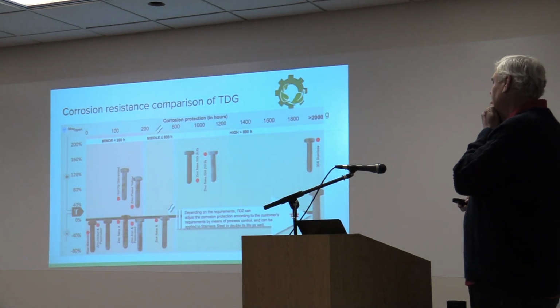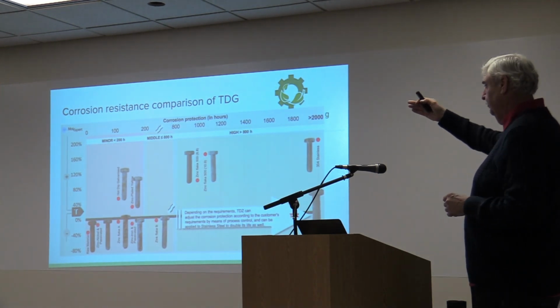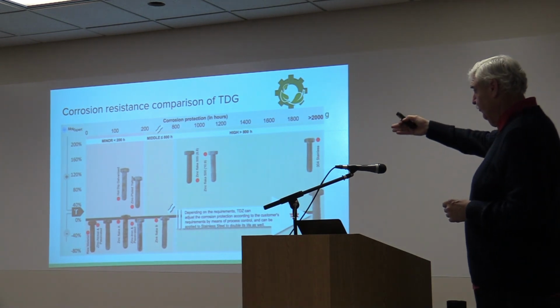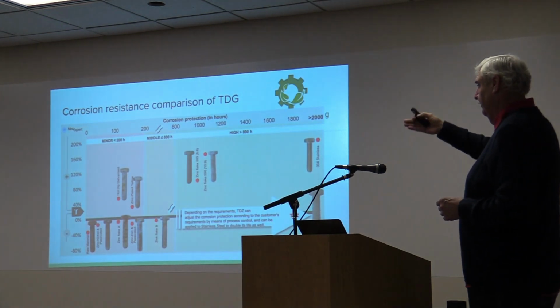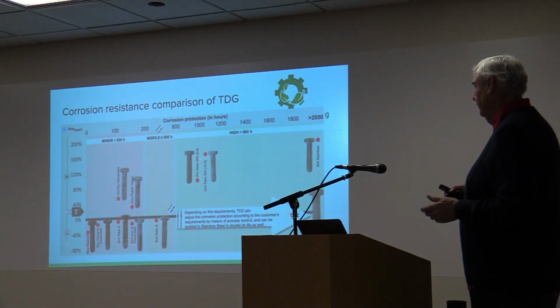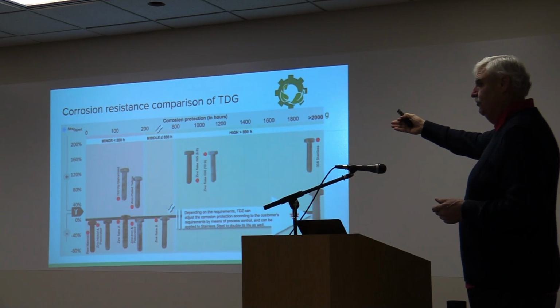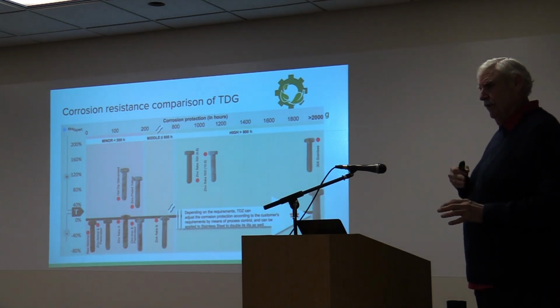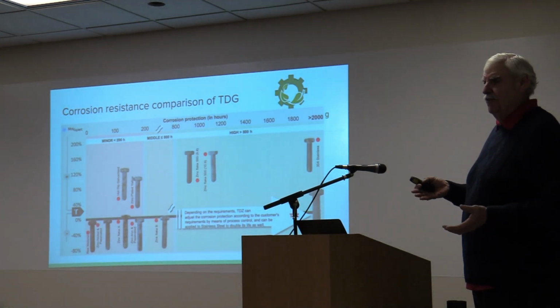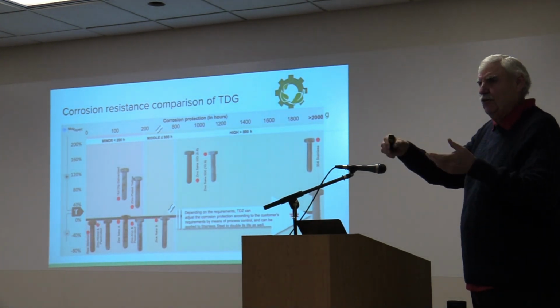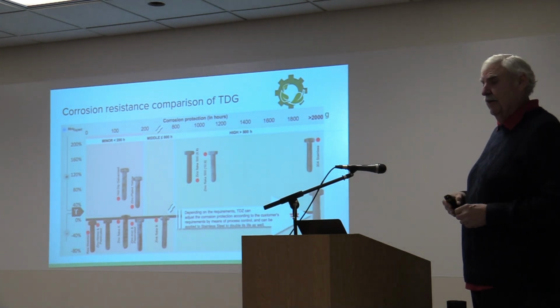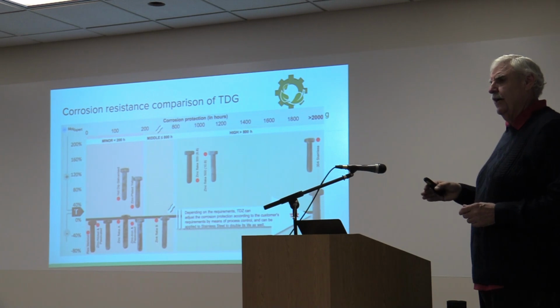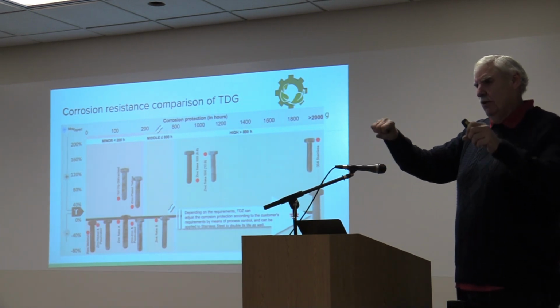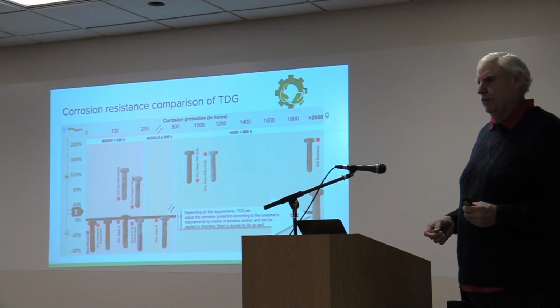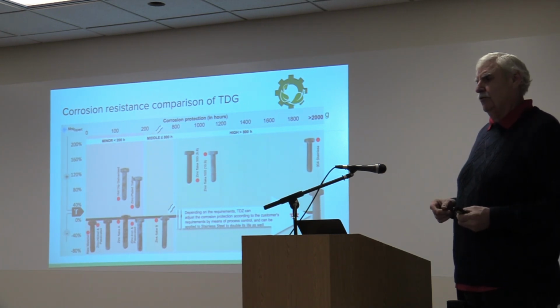So this is another really good graph that I liked. This is kind of like the salt spray across the top. And you can see the different types of processes and what happens at the various hours. So if you take zinc flake, for example, zinc flake is almost like a paint that's applied over the surface, but it's a paint, it's topical. And so if you bent it or cracked it, it cracks, and so you end up creating holidays inside of that. In this particular case, I'm going to show you an example on a rock anchor, and we've actually done some bars, bent them 180 degrees. We don't crack the coating. Salt sprayed afterwards, and they still pass the salt spray.